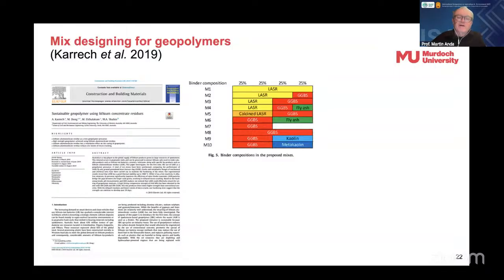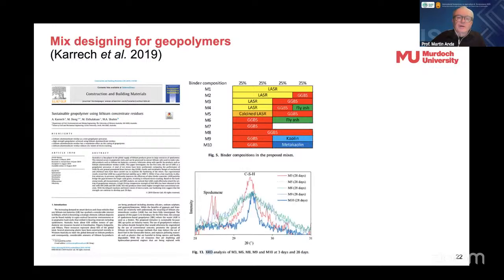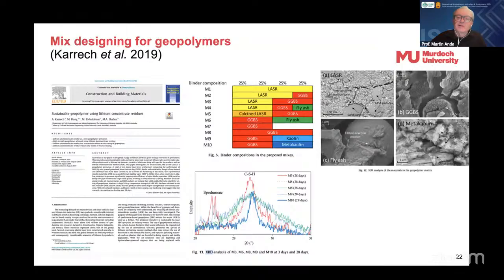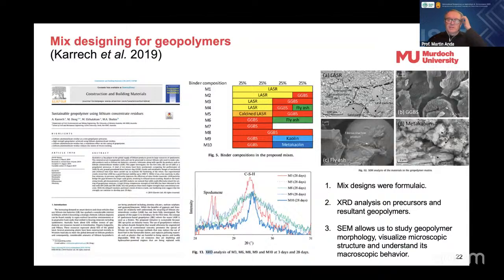So I was particularly interested in finding new mix designs that did not rely on adding any blast furnace slag. And so we are now relying more on mixes with fly ash and kaolin, and without any blast furnace slag at all. And so this is just showing this chart here that Ali Karrech has done, just showing the typical XRD analysis spikes that you're looking for in the geopolymer product, and the SEM analysis that you look for in both the precursor materials and also in the product afterwards. And this scanning electron microscope allows us to study the geopolymer morphology, the microscopic structure, and understand its macroscopic behavior. So that was really useful work by Professor Ali Karrech.